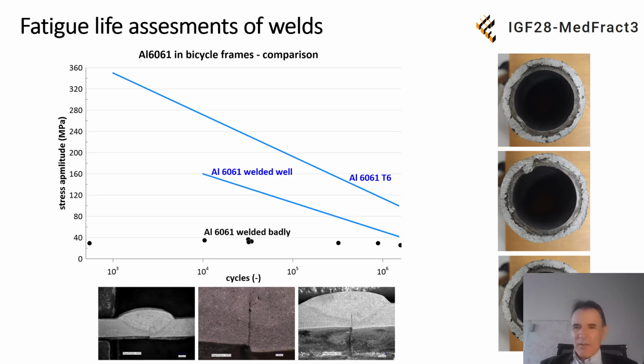Now, how is it visible? This weld process is very inappropriate, or has no appropriate parameters. The adjustment of these parameters was not appropriate and led to a very bad weld with insufficient weld thickness. And in the comparison of this diagram, it's possible to see that the basic material in the form T6, the aluminum alloy 6061, is the SN curve on the top.